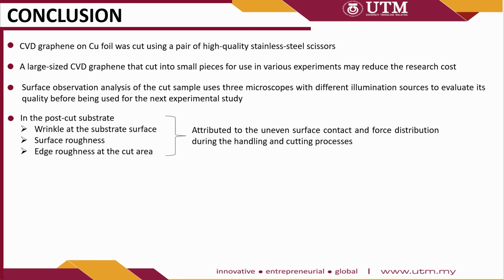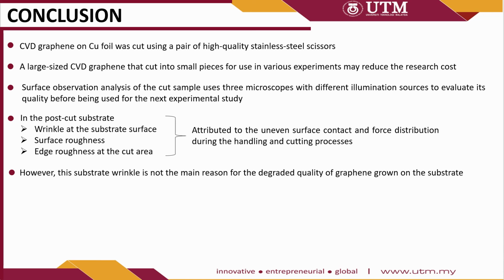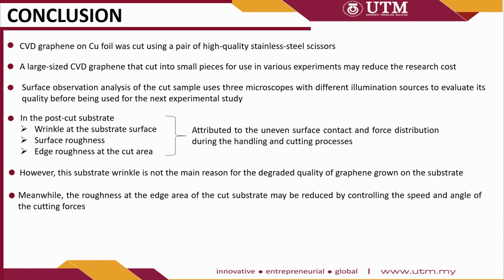In the post-cut substrate, wrinkle at the substrate surface, surface roughness, and edge roughness at the cut area were observed, which were attributed to the uneven surface contact and force distribution during the handling and cutting processes using tweezer and a pair of scissors respectively. However, this substrate wrinkle is not the main reason for the degraded quality of graphene grown on the substrate. Meanwhile, the roughness at the edge area of the cut substrate may be reduced by controlling the speed and the angle of the cutting forces.